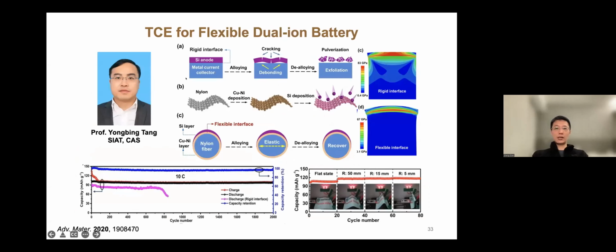On the other hand, we do this for anodes with silicon, which is used a lot for lithium-ion batteries or dual-ion batteries. And again, the problem is similar. The silicon anode will crack, and then it will delaminate from the current collector, and therefore we use our textile composite concept to also address this issue. At the same time, it brings additional flexibility to the entire cell.